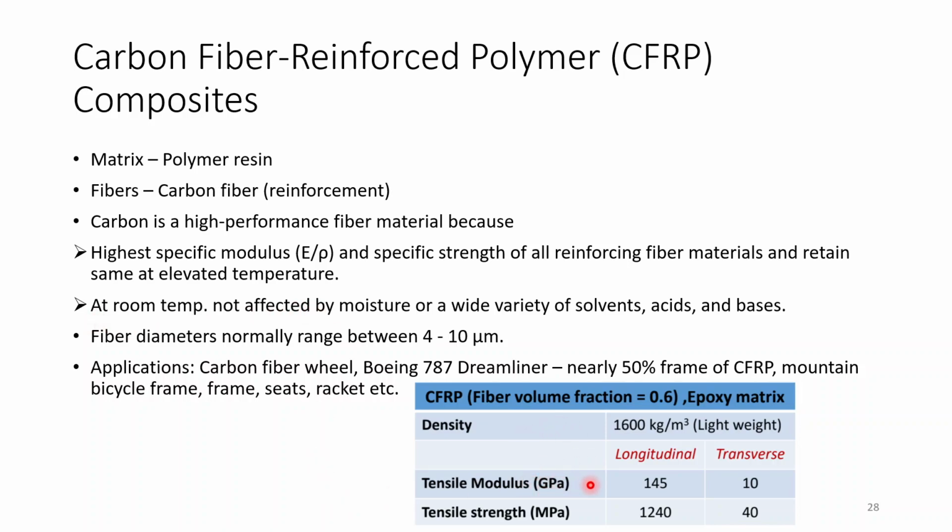Its tensile modulus is 145 in longitudinal direction and 10 in transverse direction, and its tensile strength is 1240 MPa in longitudinal direction and 40 in transverse direction.